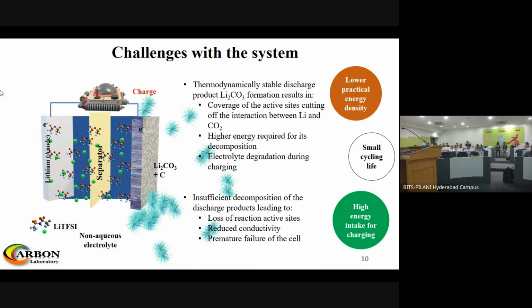Now, the higher energy required for the decomposition: if we go for the higher voltage required for its decomposition, it doesn't happen automatically. When you apply a high voltage, there are chances of electrolyte degradation. So that's another problem. Of course, you can go to the reversible side by increasing the voltage window, but then you are compromising the electrolyte stability. That's another reason the performance comes down. So there are multiple challenges involved. And of course, insufficient decomposition of discharge products causes loss of reaction sites and reduced conductivity, and ultimately leads to premature failure of the whole cell.